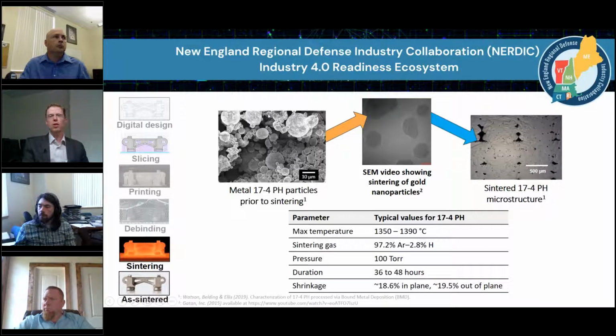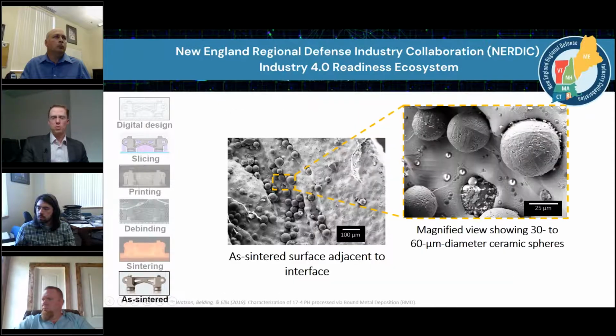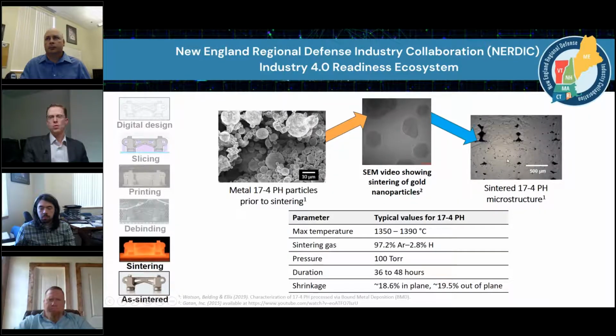So here we start off with powder, and you see there's lots of voids in this powder, and it's going to sinter down to right here. You get shrinkage in the neighborhood of about 18 to 20%, and it's a little bit directionally dependent also. That shrinkage is handled within the software, so all we have to do is provide the final shape that we want, and the software is smart enough to apply the shrinkage as need be.